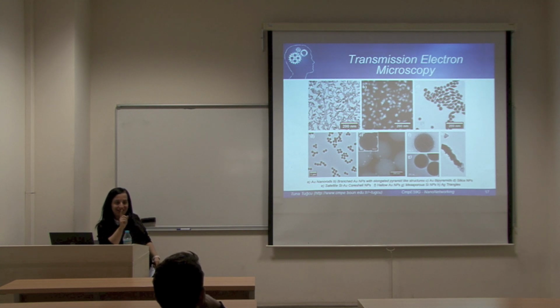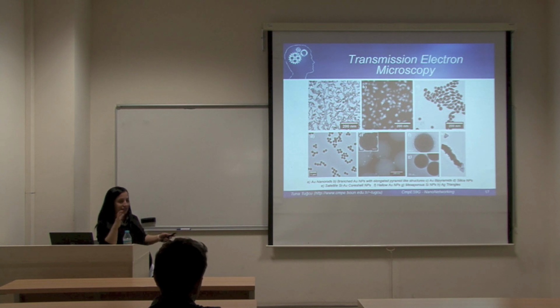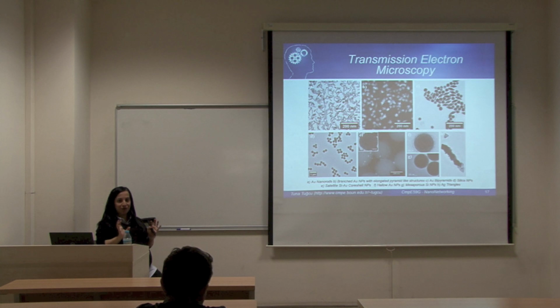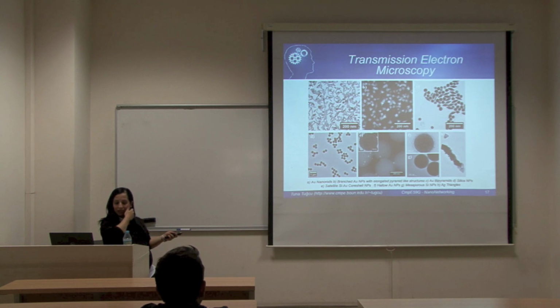Why do we do this? It's quite interesting, because silica nanoparticles are dielectric, okay? They do not give any plasmonic response, which is what we wanted. And since cost is important for industrial applications, instead of making completely big gold nanoparticles, we just fill the inside with silica and use the gold outside. And we couple the properties of silica and gold together. This is a core shell system that you can use for low cost production.